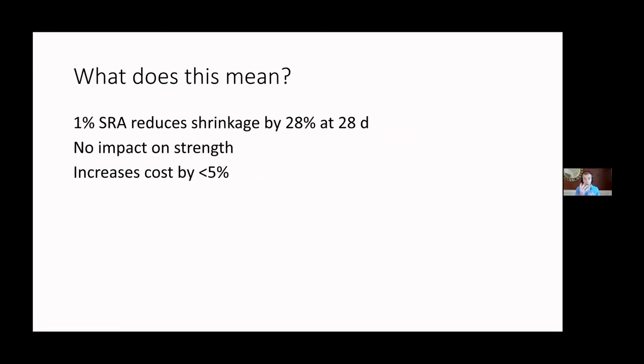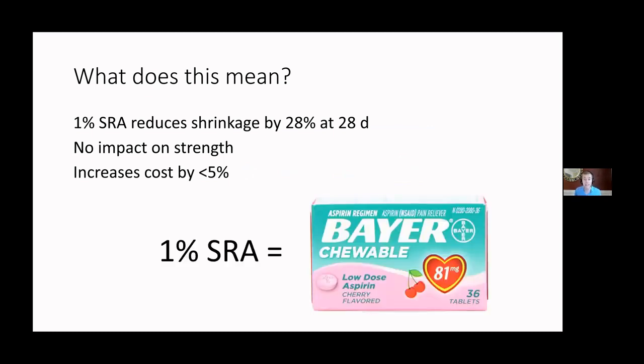This 1% shows a lot of promise. It reduces our shrinkage by about 28% early on. It has no impact on our strength. And because we're using such a low dosage, it's less than a 5% increase in the cost of a typical concrete mixture. And that is what a baby aspirin is all about. That's what we're shooting for. This 1% is definitely a baby aspirin.